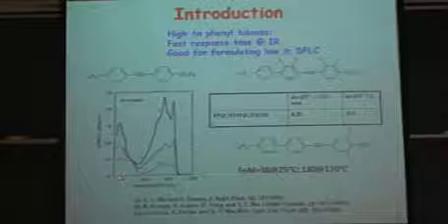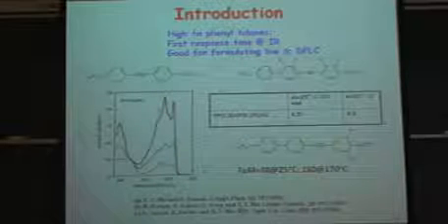We measured its absorption spectrum. There are two peaks. One is at about 200 nanometers, and this is induced by the sigma bond in the molecular structure. And this one is about 300 nanometers because of resonance wavelengths. And the longer the resonance wavelength, the larger the birefringence.